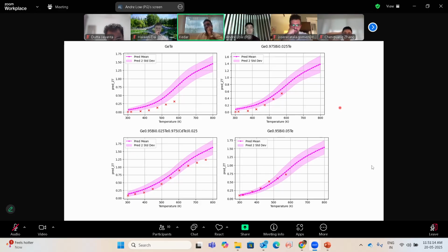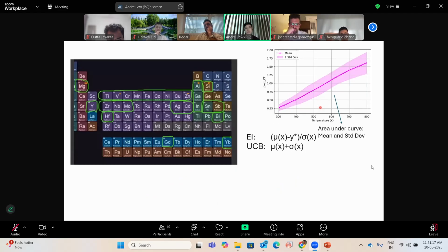Okay. So the idea now is that we can actually do the optimization. So we had a very baseline screening. Chengguang and Pepe had a talk, and they decided on these dopants of interest that we highlighted. So I came up with a permutation script that would iterate through up to 3 different dopants onto germanium telluride. So the base material is the same. Oh, so all of this is only germanium telluride data? Only germanium telluride candidates. Okay. Then we would have anywhere from 1 dopant to 3 dopants, in step sizes of 0.1. I'll show you later some of the candidates.